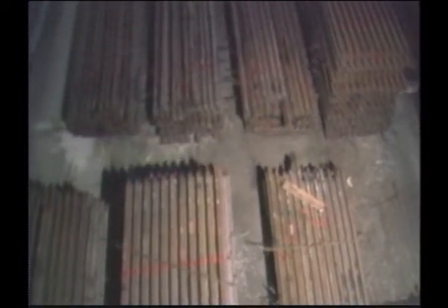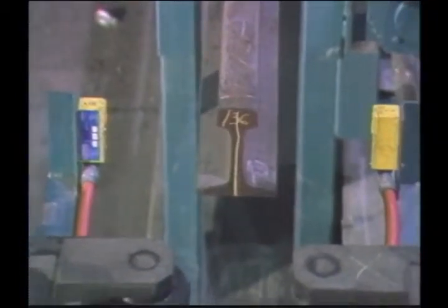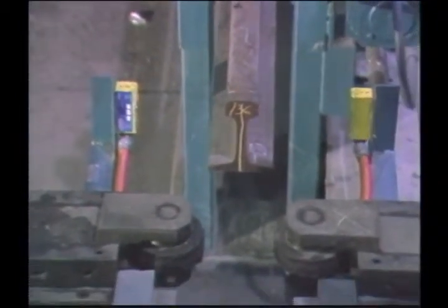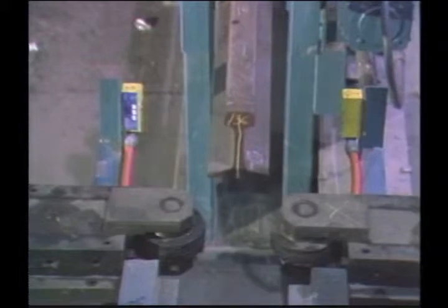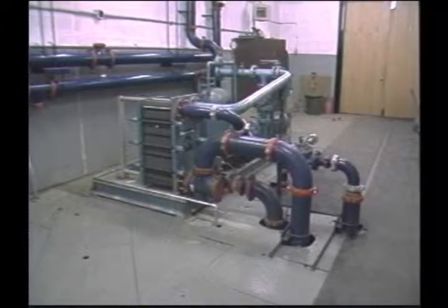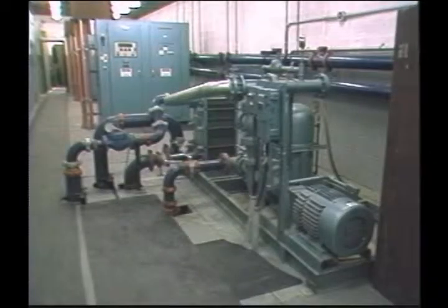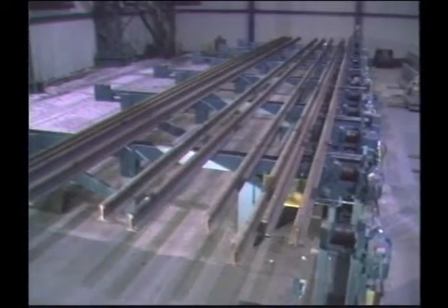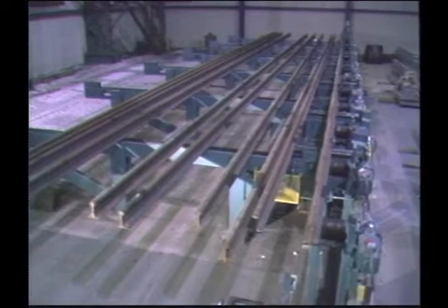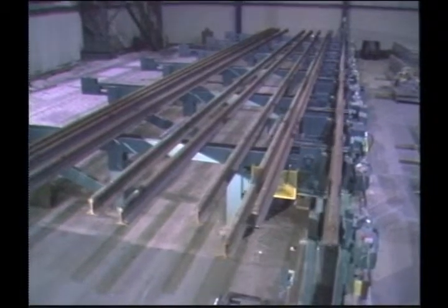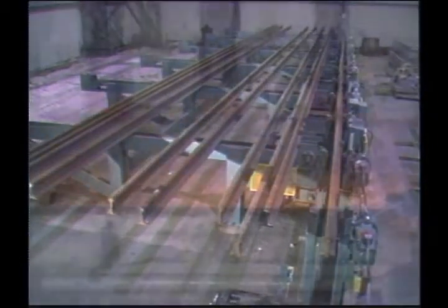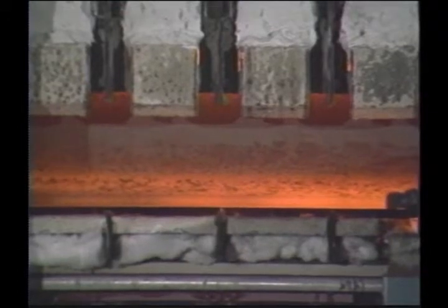The Permatrack process is capable of producing 50,000 tons of heat-treated rail per year at a production speed of 5 feet per minute. This production rate can be increased by up to 3 times with additional power and quench modules. The process line has been designed to fit into the material handling process at the rail welding sites of the railways themselves. New welded strings comprised of standard carbon rail can be continuously heat treated to produce a seamless string of deep head-hardened 388 Brinell rail.